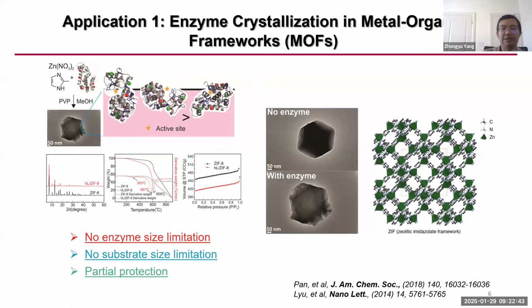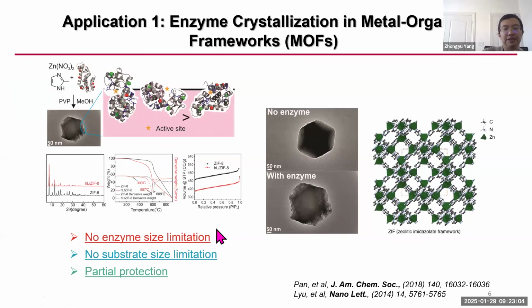Now, if this hypothesis is correct, then we have a way to immobilize enzyme with no enzyme and substrate limitations, and we offer partial protection to the enzyme, which in our later works proved to be very handy, very solid. So to prove this hypothesis, we immediately tried a lysozyme enzyme, which degrades bacterial cell walls, and cell walls are micrometer order, which cannot diffuse into these small pores. So we see activity that proves the enzyme is partially exposed.